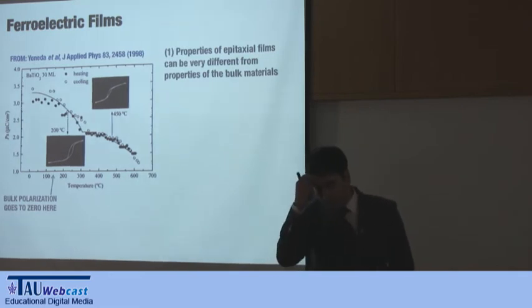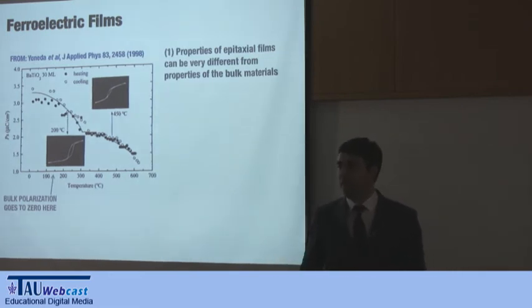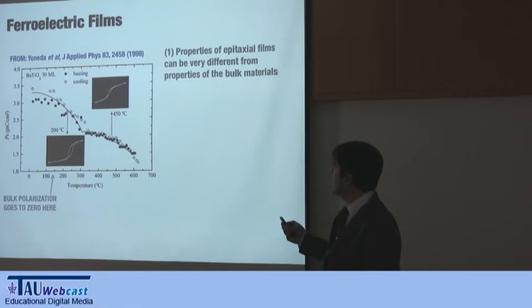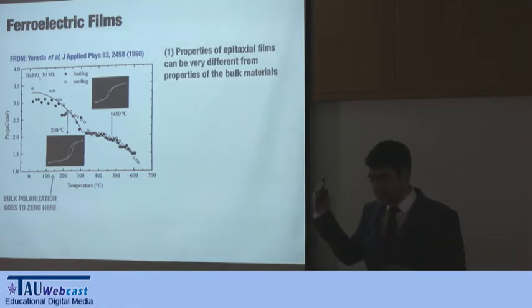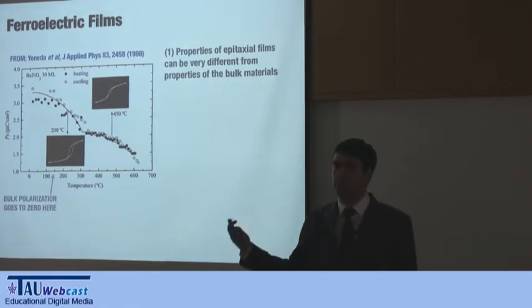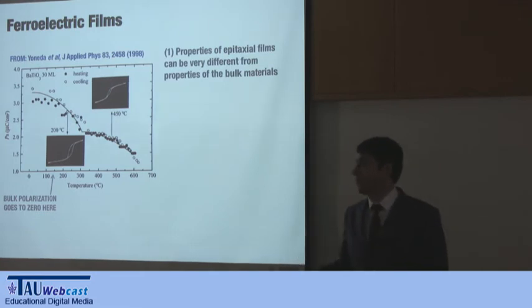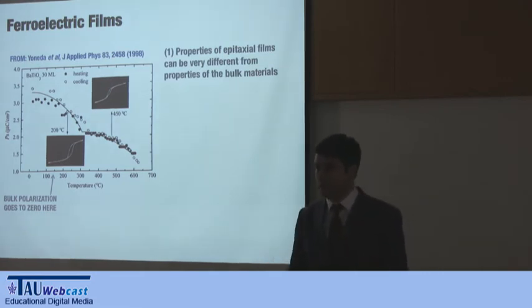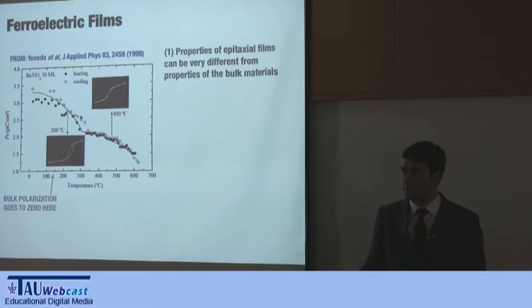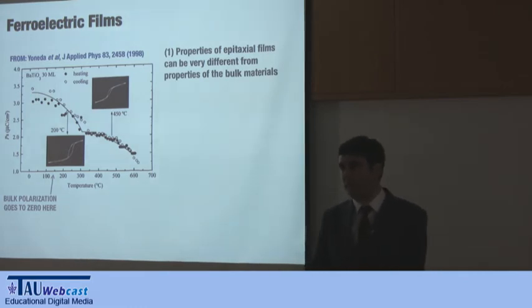So the study I'm showing here is not for bulk ferroelectrics, but for ferroelectric films. And what is particular of them is that when you grow this, what I say here is epitaxial films. These are coherent epitaxial films. When you grow them, the properties of them change, because they are on a substrate and they have to adapt to it. By choosing which substrate you have, you can choose what properties you have.